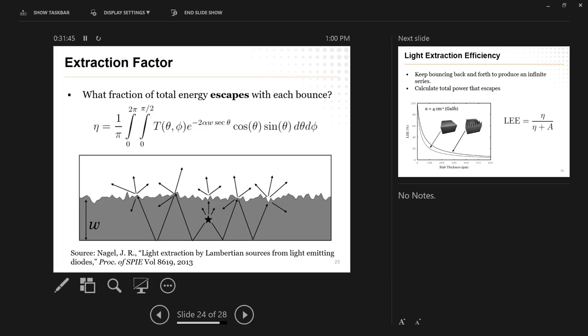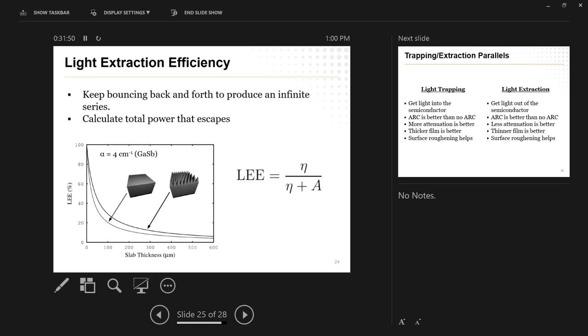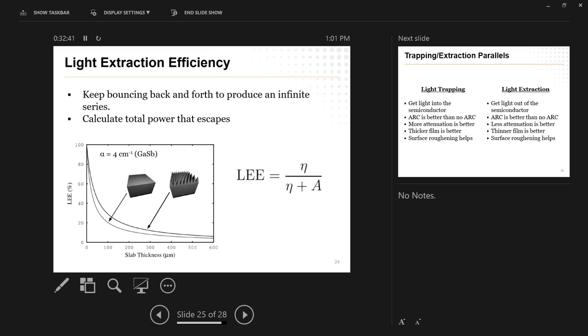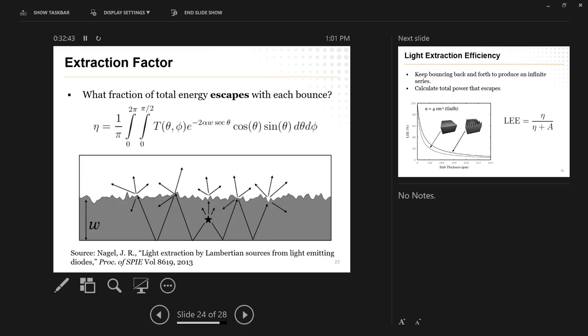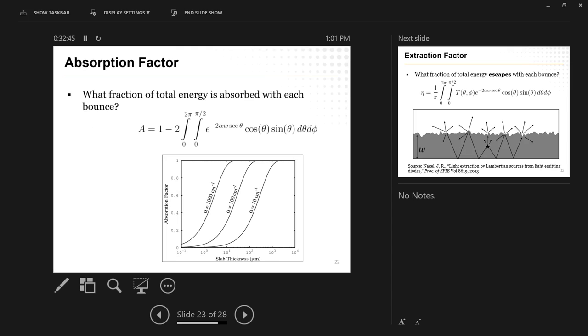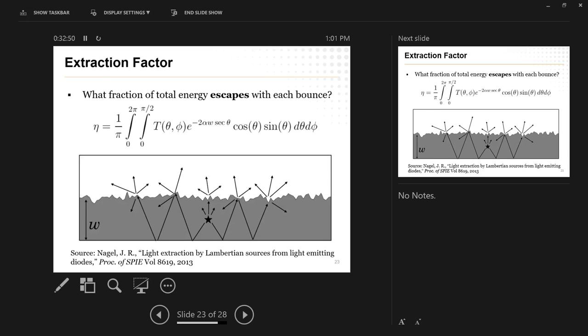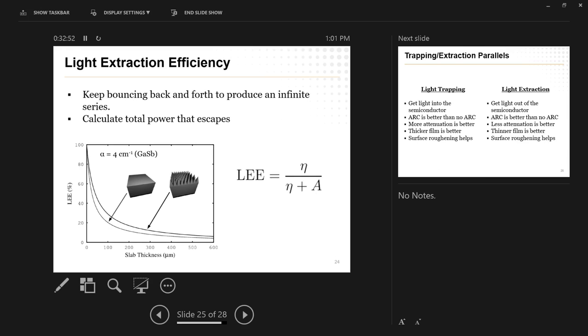So I did another little follow-up paper right there to show some of that. And the next step is you just do that infinite geometric series, and you actually get a nice straightforward answer that looks like this. So this is the fraction of energy that leaves into the surface when it hits the top with each individual bounce, and then this is the absorption along the way in between. So that's just the result out of that geometric series, and you get some nice little results here. So this is a simple case. I think you have the bottom being roughened, and the top is just a flat surface. And I did some simulations. You see where I added like little cones here to try and get the light to come out. And all that does is just play with these numbers here, depending on your thickness. And in particular, we were interested in gallium antimonide, which is great for making infrared LEDs. And at the end of the day, you have the neat thing about this is you just have two numbers here that you can graph as a function of your thickness, and it's just two integrals that you have to crunch on to get those two numbers there. So even if you do this numerically using like trapezoidal integrations, it's a pretty straightforward extrapolation.